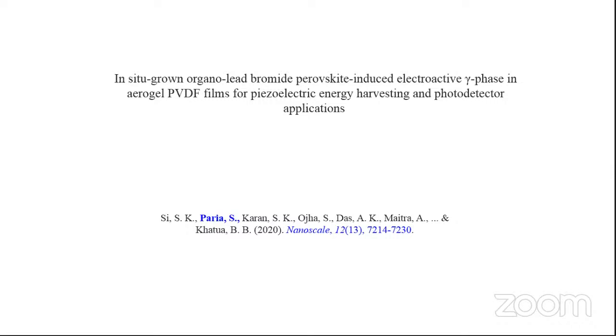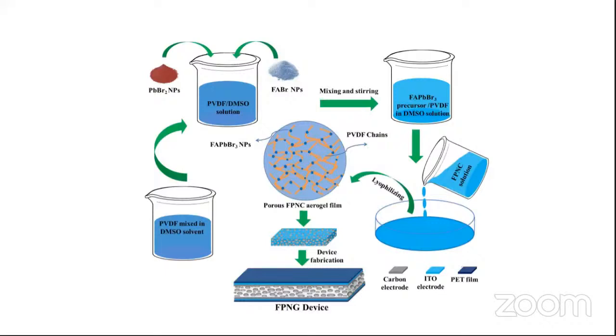One is organic-inorganic perovskite, another is ferroelectric polymer. So here we have chosen an in situ process for the formation of organic-inorganic perovskite. First, we have taken a definite amount of PVDF in DMSO solvent. After that, we have mixed two precursors, formamidinium bromide and lead bromide.